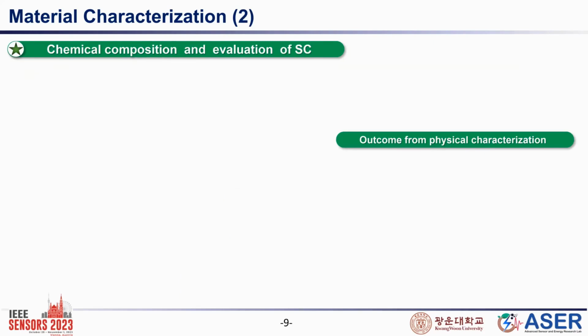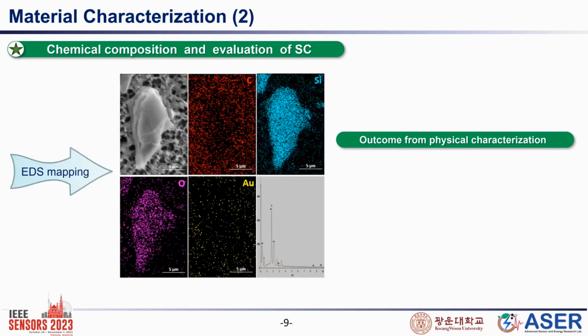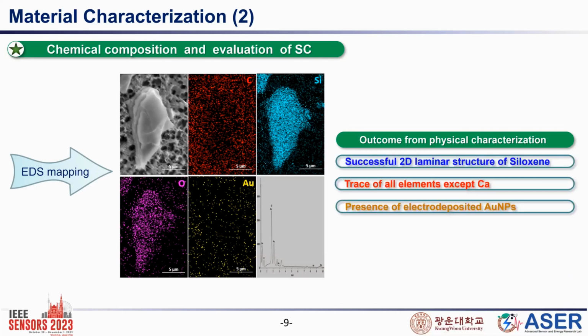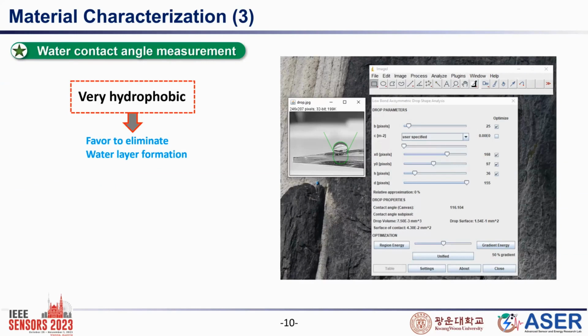And now I would like to go to the material characterization. So this is the EDS image of our material. It shows all the desired elements except the calcium, because we have etched the calcium part. So the presence of carbon, silicon, gold nanoparticles, and oxygen come from our proposed solid contact material. So we can say that we have successfully done the siloxene synthesis, with trace of elements except calcium and the presence of electrodeposited gold particles.